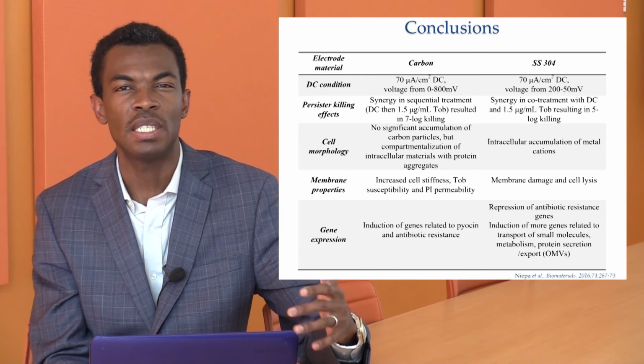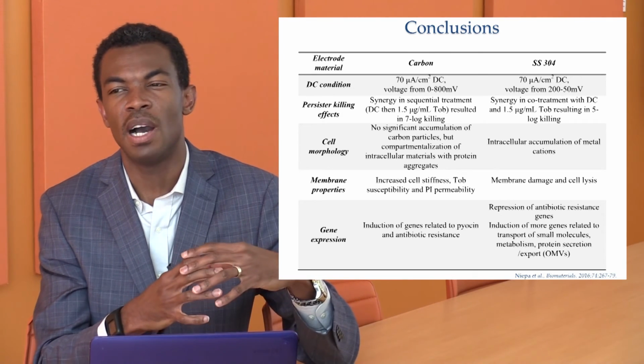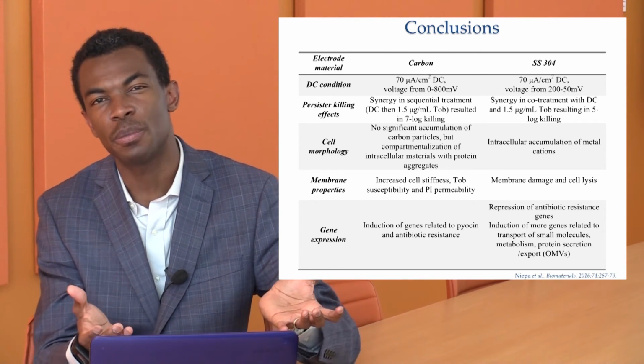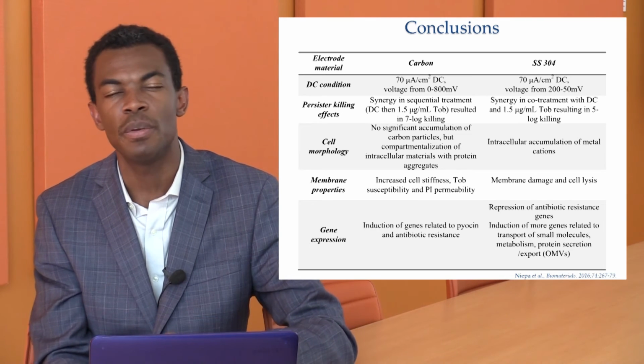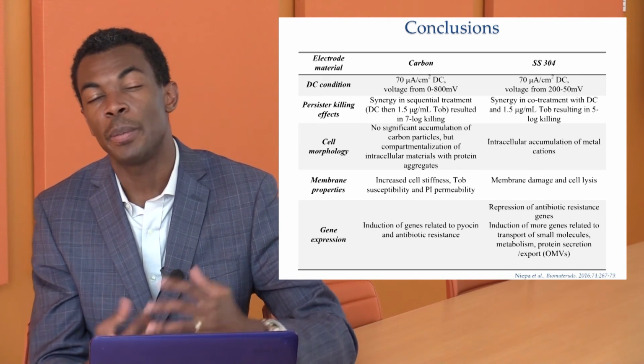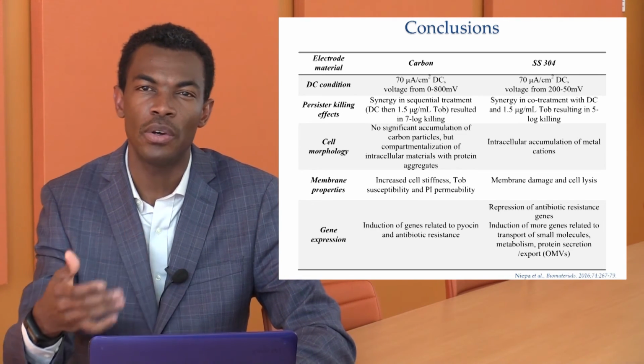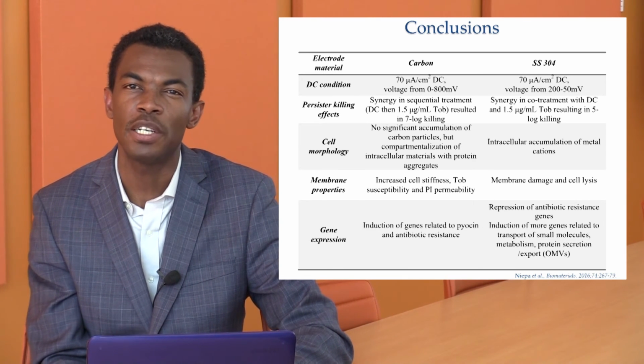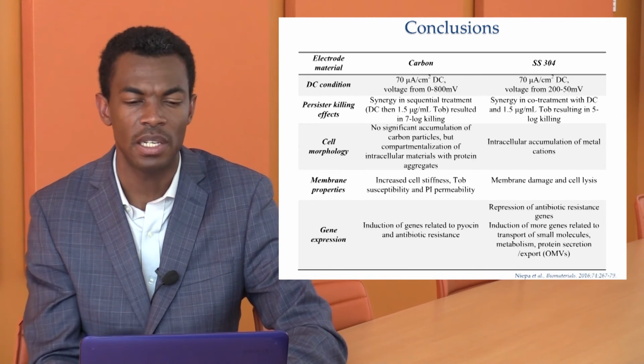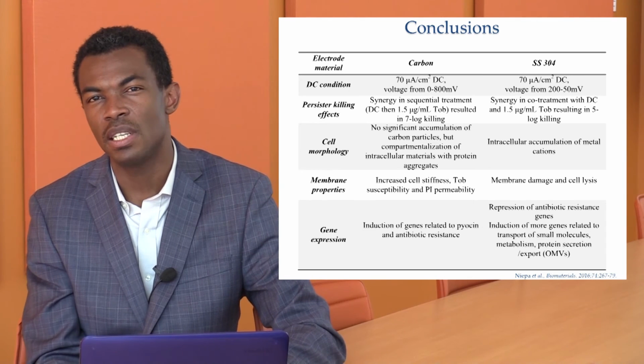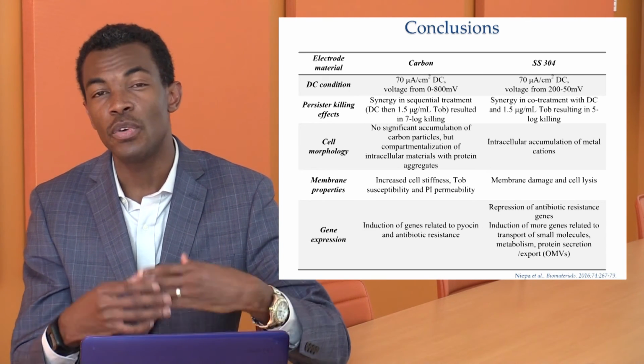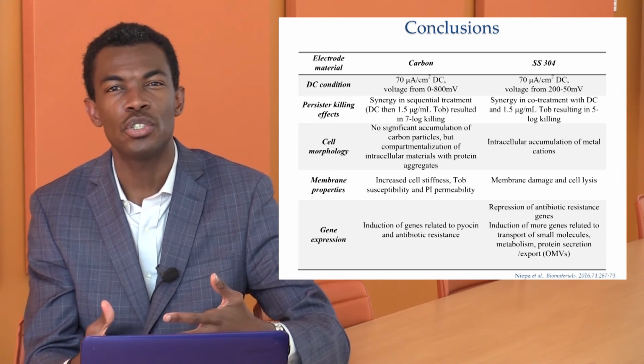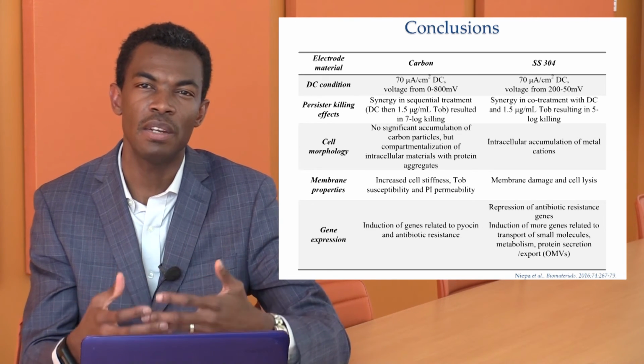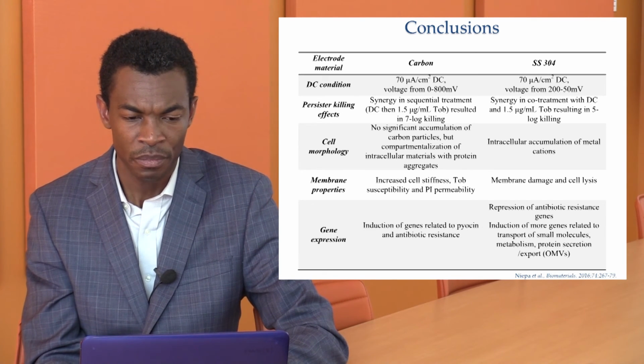Carbon electrode tends to affect the cells by affecting the surface property of the cell, disrupting the membrane function of the cells, and later allowing a sequential antibiotic treatment to completely eradicate the cells. As for the treatment with stainless steel, we are able to understand that if we perform a treatment in combination with antibiotics, we can kill the cells to a higher level.